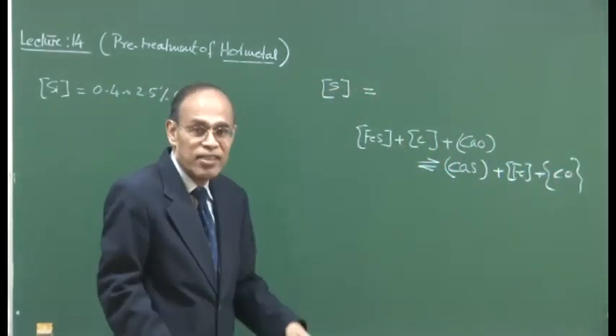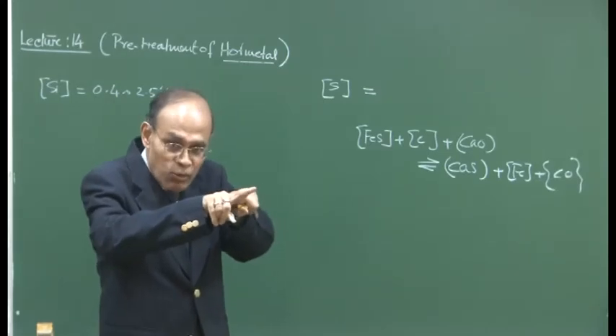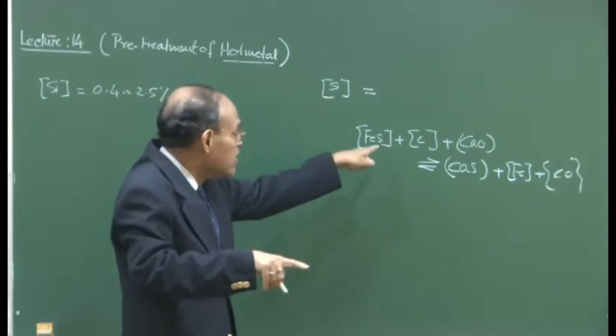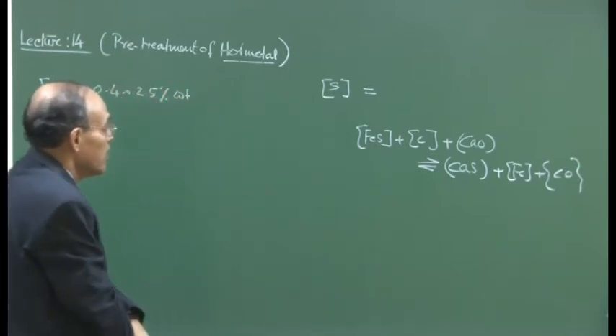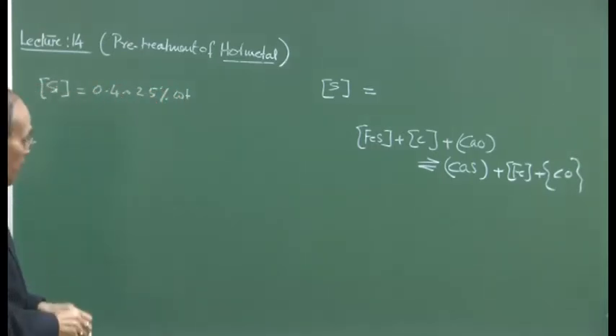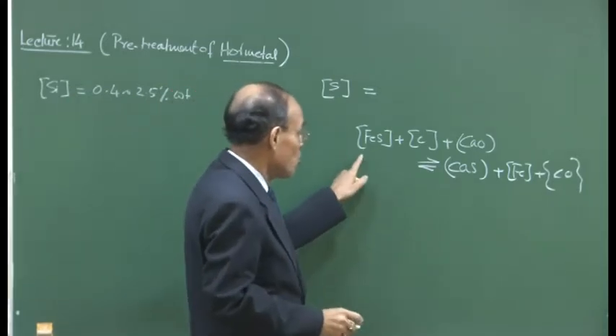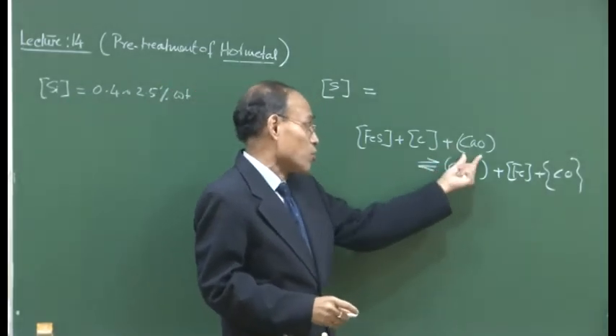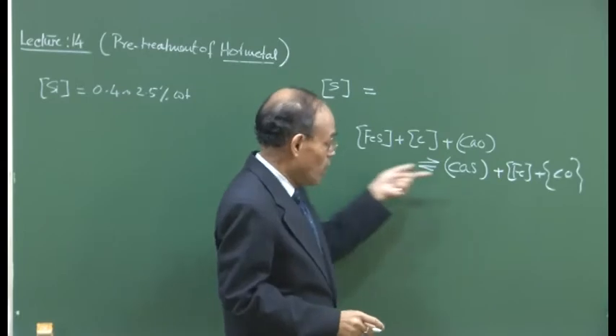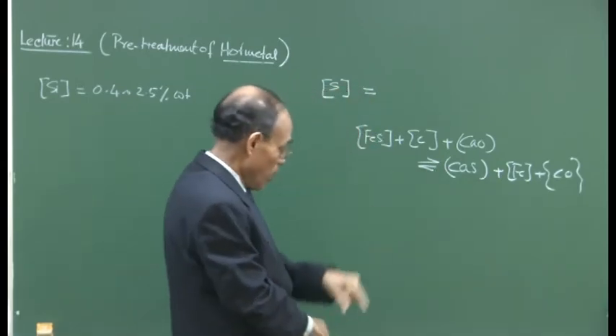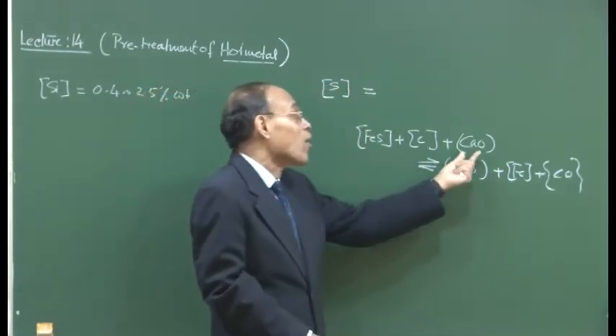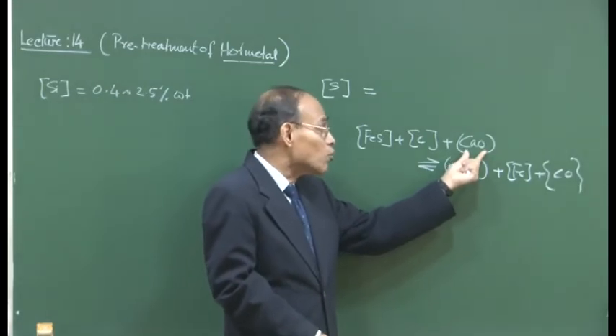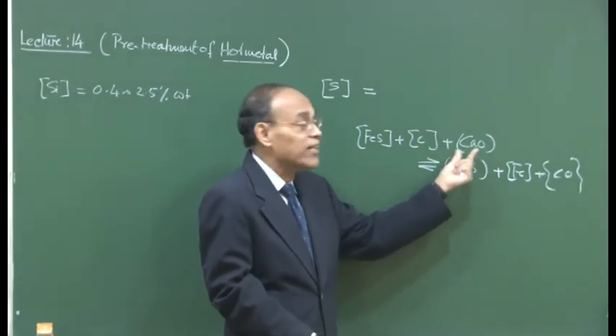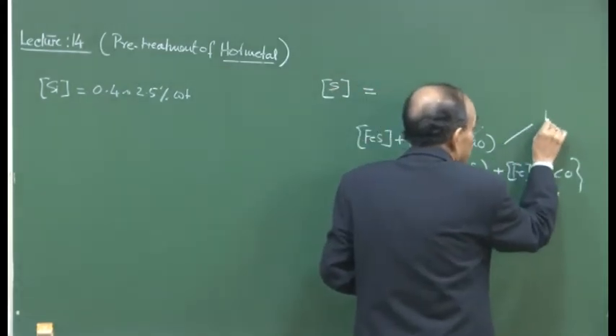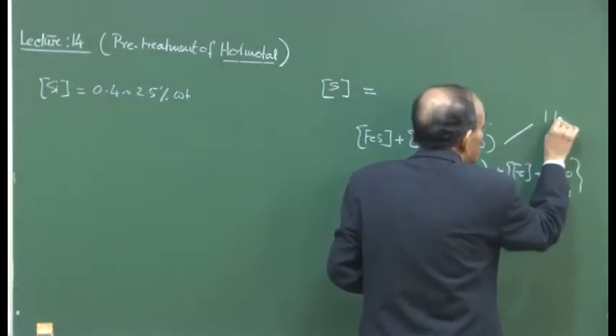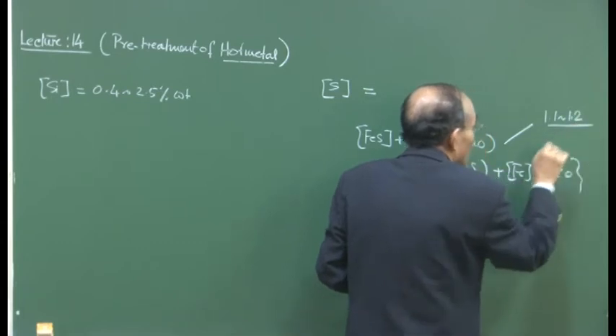This is a slag metal reaction. It takes place where the metal comes in contact with the slag, and there is an interface. It is at that interface that this particular reaction is taking place. It is clear that the more the concentration of CaO in the slag, this reaction will have a tendency to go from left to right. But as I said, we may not be able to have a very large CaO content, and that is why, if you remember, I said that the blast furnace slag basicity is 1.1, 1.2, something of that sort.